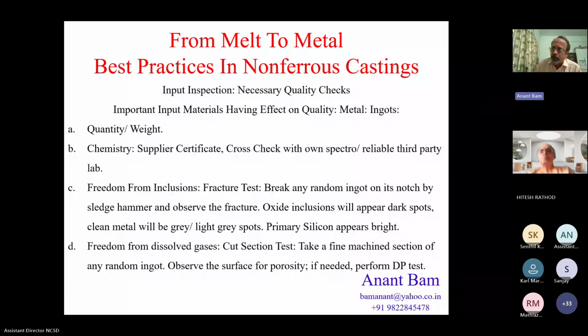Usually, when you select an ingot, I have told you to take any random ingot. There are some quick checkpoints. If you find that the ingot is cast in 1 or 2 or more layers, then you have to be very cautious, because in an automated ingot caster with a caster wheel and caster line, every ingot is cast in a single layer. So if there are layers, then it is cast manually. And when there is manual casting, there is a chance of adulteration or other quality issues.